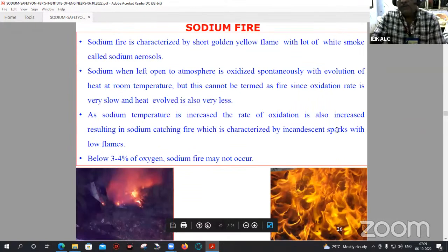So coming to sodium fire, you can see the color of sodium fire. The basic difference between a general fire and a sodium fire is the color. It's golden yellow in color. With oil fire, the only difference here, you can see, is that it's blackish, due to the carbon. Here the carbon content is very low, it's pure sodium. Only less than 25 to 30 ppm of carbon is there in the sodium. That's the purity level we maintain.